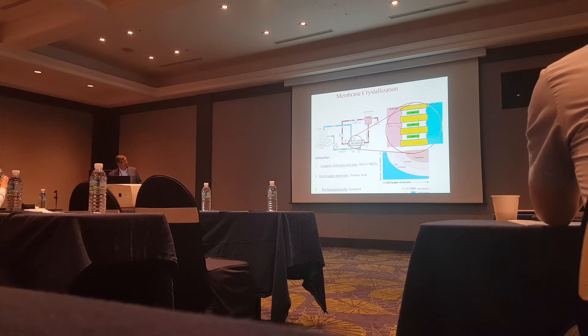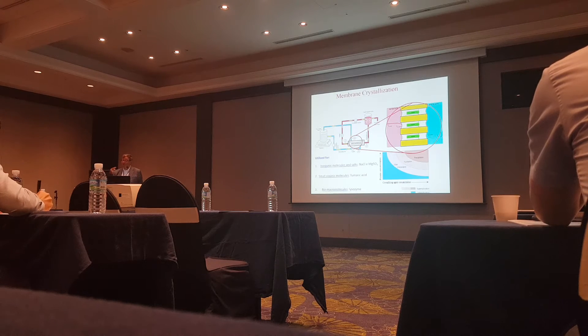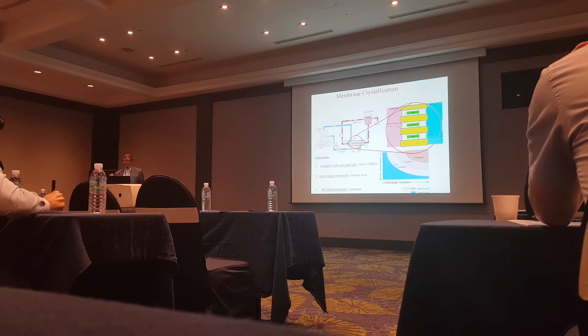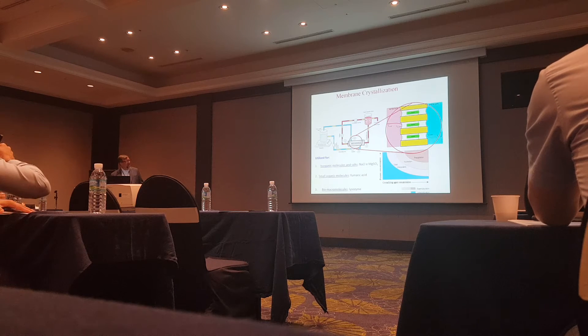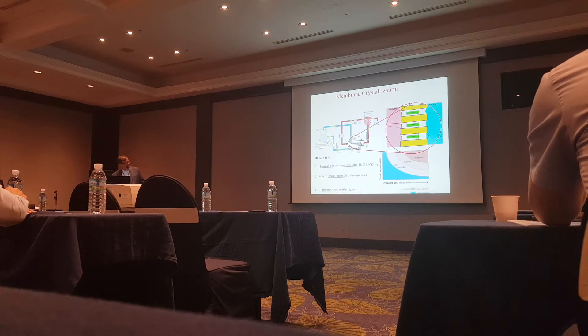The key part to study carefully is how to induce heterogeneous crystallization in the membrane module while allowing crystal growth to take place in a different part of the system to minimize fouling. It seems difficult, but it is not. Today many groups around the world are working on this system, and if you know what you are doing, it can be done. Crystals, in some cases, actually help control fouling — they promote local turbulence, which minimizes concentration polarization. With the appropriate configuration, you can remove crystals continuously and crystallize inorganic molecules, organic molecules, enzymes, and proteins.